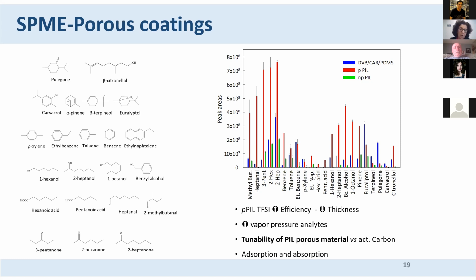On the other hand, realize another thing. The advantage of having a PIL that is porous is that the pores are charged. And so we can play around with this also. So the pores inside of a cationic PIL are typically positive. And so here you can see that it's much easier to extract polar compounds than to extract non-polar compounds, showing that we could really tune our PIL porous material to extract certain compounds. Okay, so here I made a comparison between the dense and the porous for solid phase microextraction.